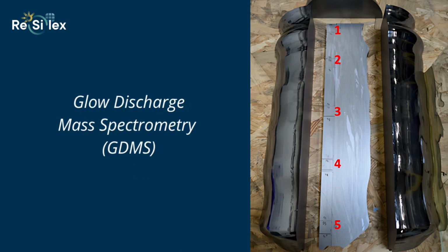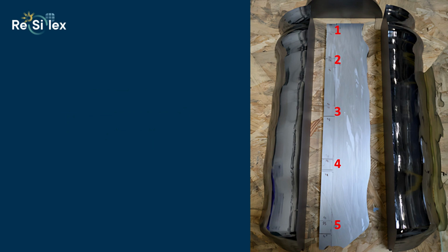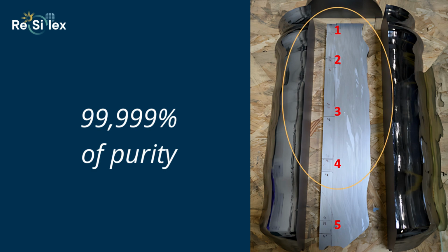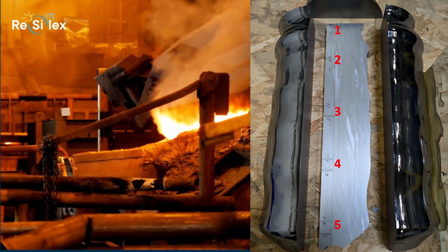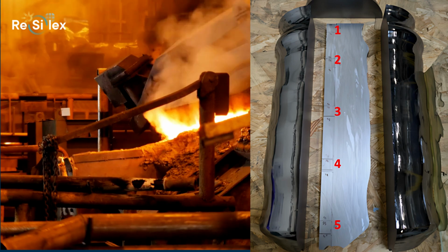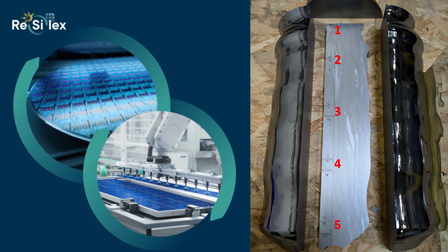The results confirmed that this recycled silicon reached a level of purity of 99.999% on the major part of the ingot. This high purity part of the ingot was accepted for being used in CEA's Czochralski furnace as feedstock to grow a new ingot, suitable for solar cell applications.